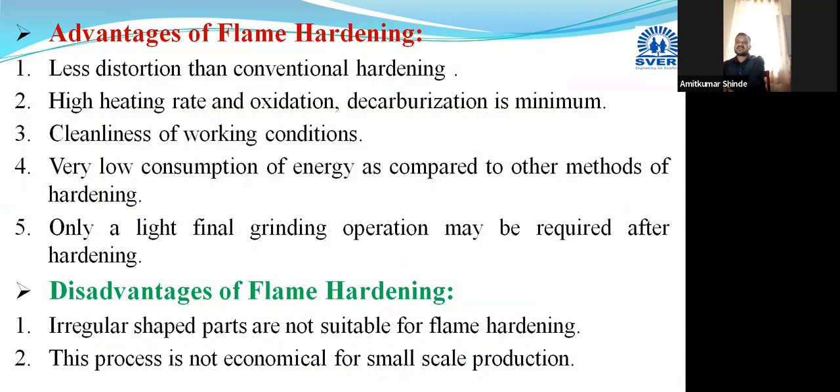And what are the advantages? There are some advantages of flame hardening. Distortion or cracking is very little compared with conventional hardening. The heating rate is very high, and the amount of decarburization, that is loss of carbon, or oxidation is very minimal. The cleanliness of the working conditions is very high, and energy consumption is very low compared with conventional hardening. Then for the finishing operation, only a light final grinding is required.